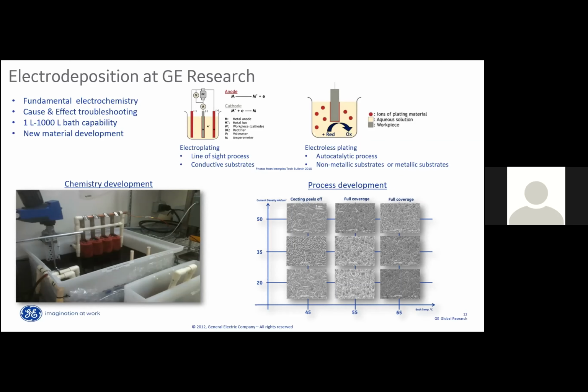The conventional electroplating, you can plate them up to thousands of microns. It is typically done on conductive surfaces, and it plates along an electric field. So it's a line of sight process. There is electroless plating, which can be done on non-conductive surfaces to make them conductive.